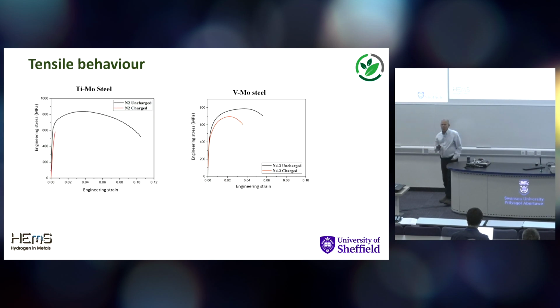Moving on to the mechanical properties of the material, really quite different behavior between the two steels. I mean, they're almost identical steels. They've got the same microstructural scale, they've got the same precipitate type, it's an MC type carbide, same precipitate size, same precipitate number density, but they behave very differently. So here's the titanium moly steel. It's got a higher strength, it's got a pretty decent ductility on the black. As soon as you charge it, it breaks at yield. It completely snaps at that point. It loses all its ductility. On the right, the vanadium moly steel is not quite as strong, not quite as ductile, but when you charge it with hydrogen, it retains some ductility, albeit it is still reduced.